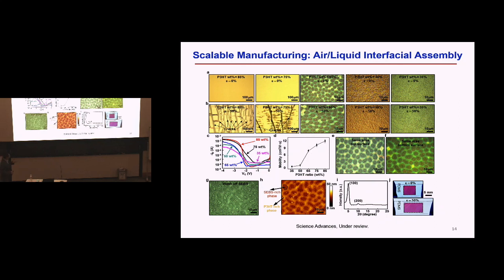The take-home message here is that we found about 65% of the organic semiconductor mixed with the rubber, a small plastic rubber, SEBS. This structure forms network structures that allow mechanical stretch, and you can still retain pretty good device performance. So the take-home message is that we now have the knowledge to create rubbery semiconductor materials.